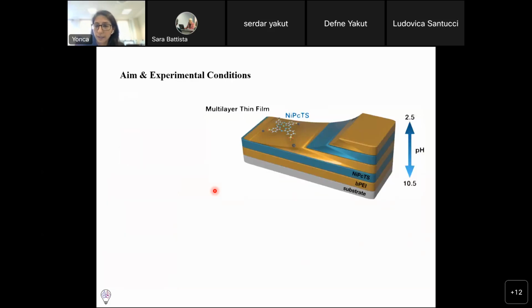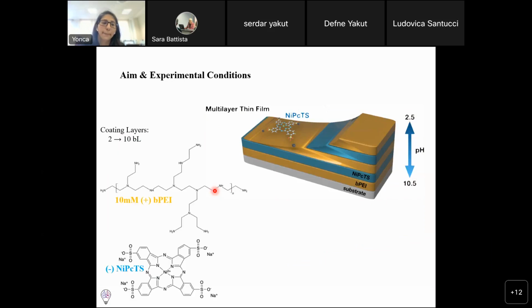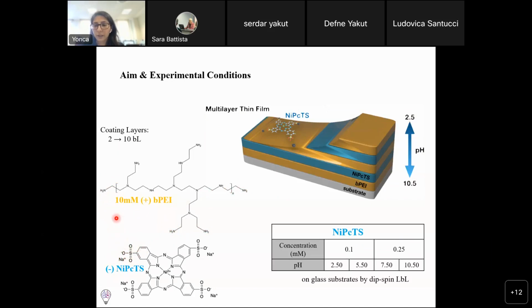So, as I said, I was changing the pH of the phthalocyanine only. And these are the chemical structures of the branched polyethylenimine. So you can see the polymer chain here and the amine groups attached to the branched polyethylenimine. And the phthalocyanine has the sulfonated groups, and that's why they have electrostatic interactions, and they are both water soluble. And actually, these are the conditions that I've studied.